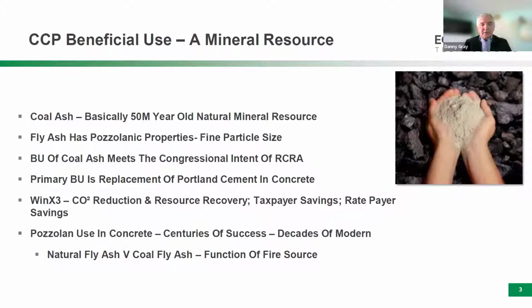So that mineral component is where we see the value, because it has pozzolanic properties, which means that it will set, it'll add strength to concrete. It's important because it's already ground into a fine particle size, and it has the right constituents in order to be a pozzolanic activity within the concrete matrix. So it has tremendous value because of it. It's a powder, as you can see in the photograph to the right. It is a face powder type consistency material, but the fact that it's that fine powder and dry and usable as a replacement for cement is where the value comes in.